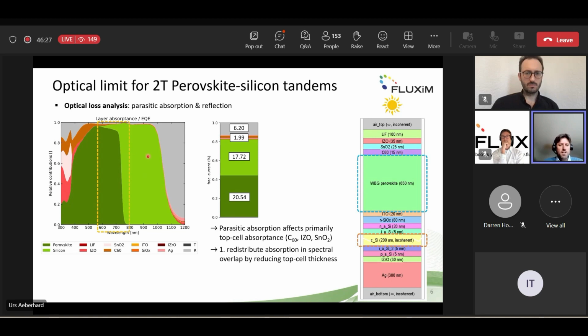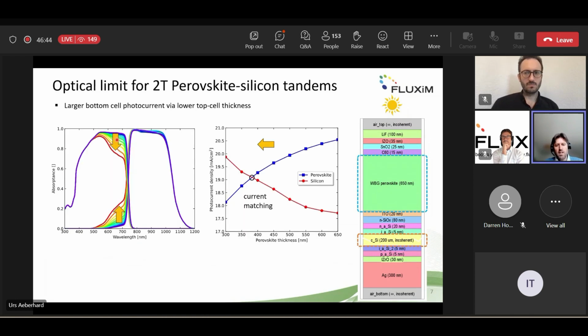So what we can see is that there is a domain where there is an overlap in absorptance, and this can be used to redistribute the absorption from the top to the bottom cell to mitigate this mismatch in the current. And of course, what you have to do is to reduce the perovskite thickness, which increases the silicon photocurrent until you reach a current matching condition.